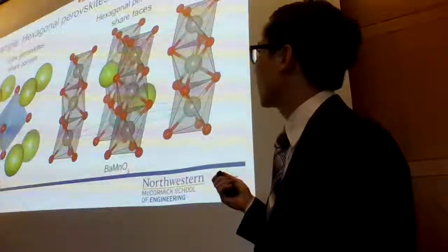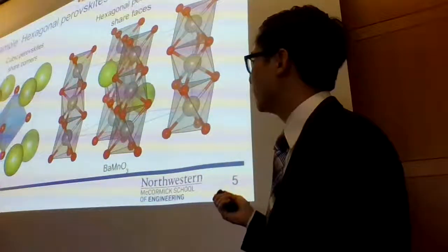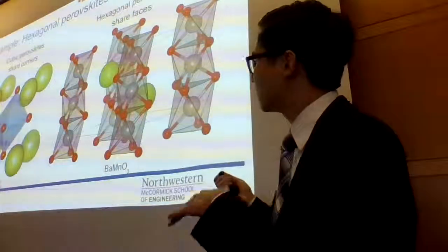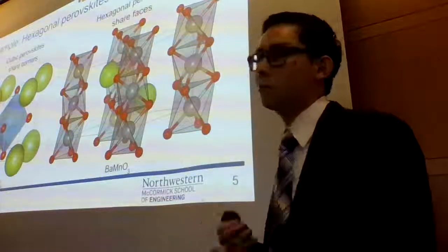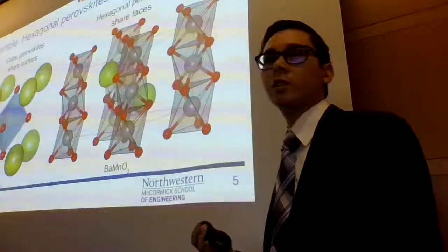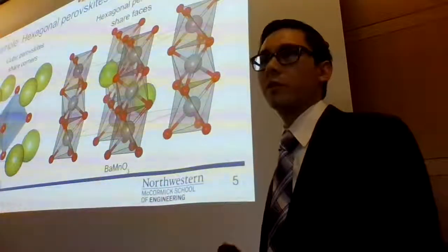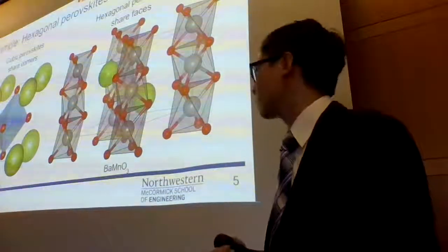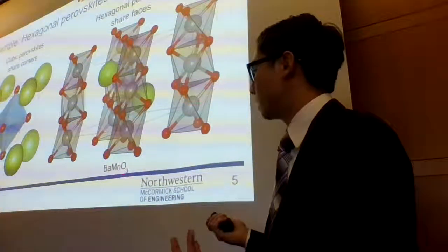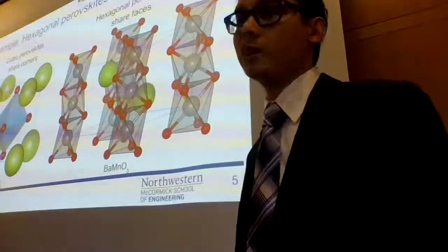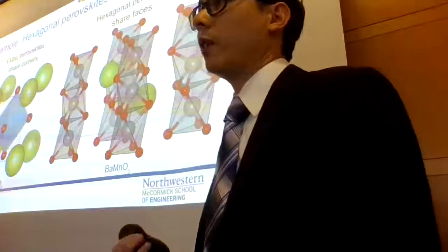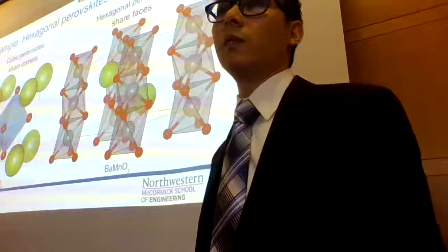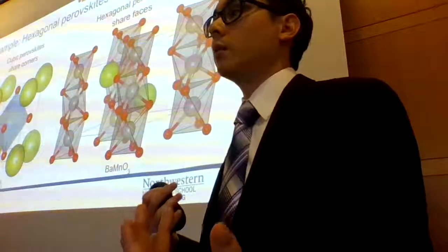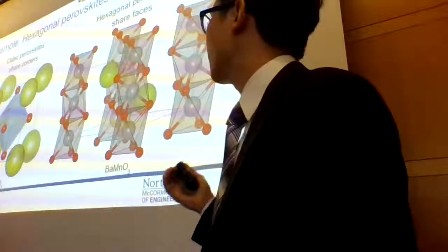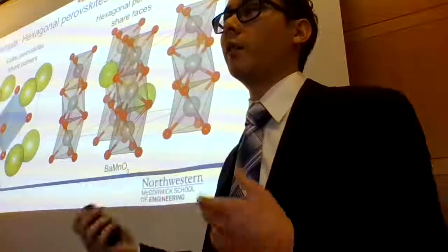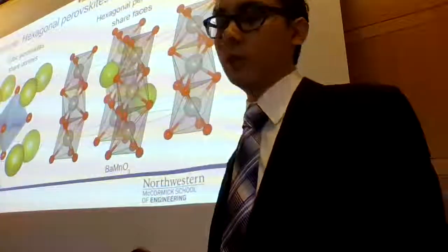And I'm going to be contrasting that with these hexagonally face stacked chains of compounds. They're not as commonly observed, actually. By Pauling's rules, these are relatively rare structures to be found in nature. An example composition would be barium manganite, but barium nickelate also has this. And as a result of the rarity, they're not as well studied. And we wanted to know whether the structure that's unique to these compounds might be of interest for, say, tailoring the electronic properties or other properties of these materials.